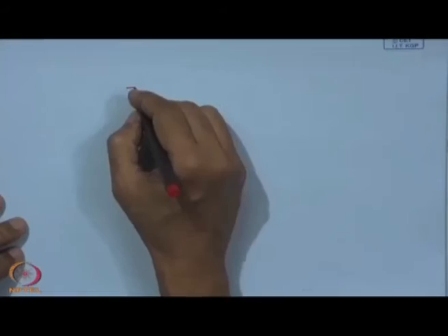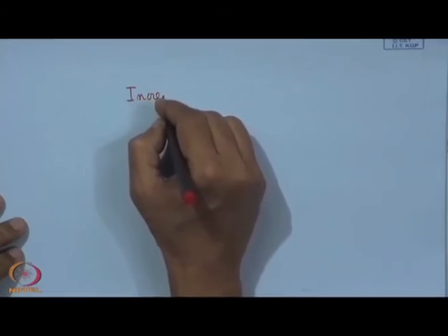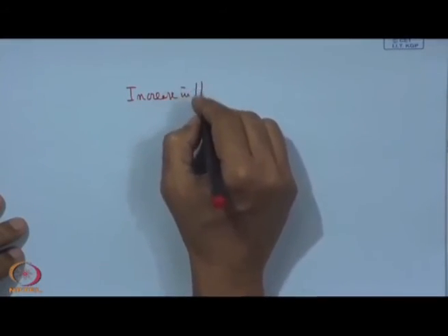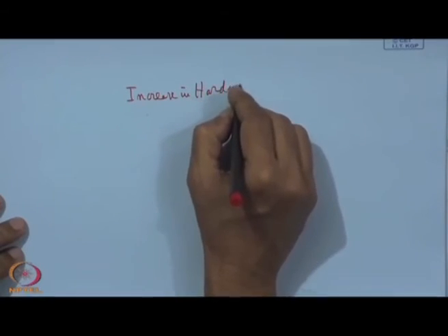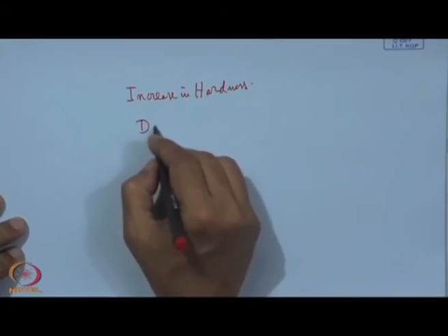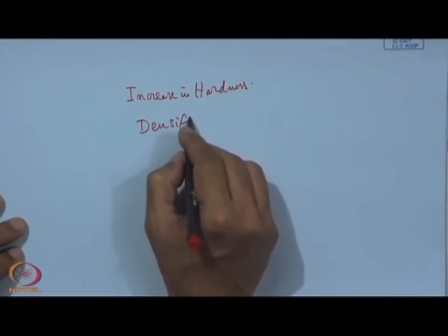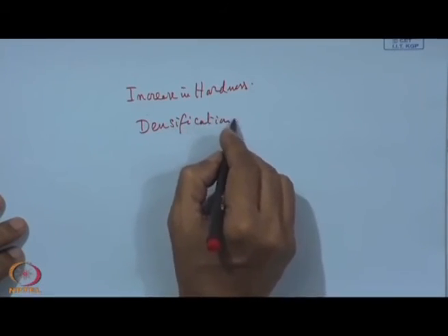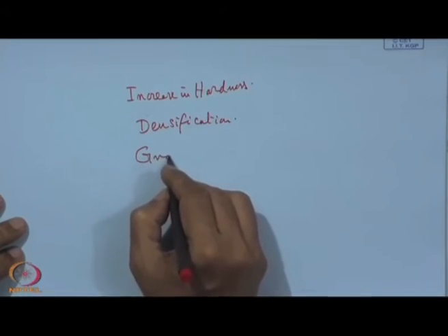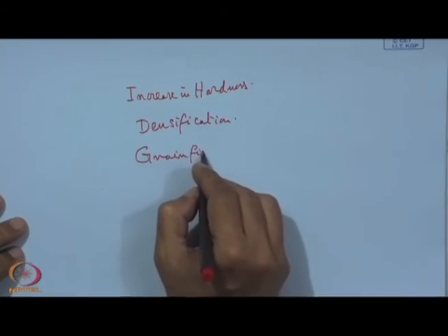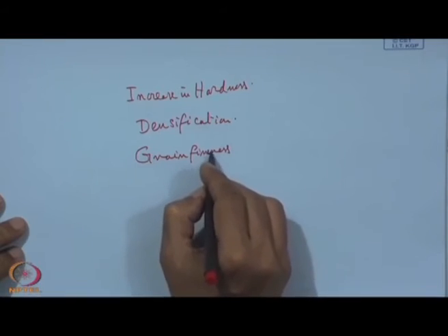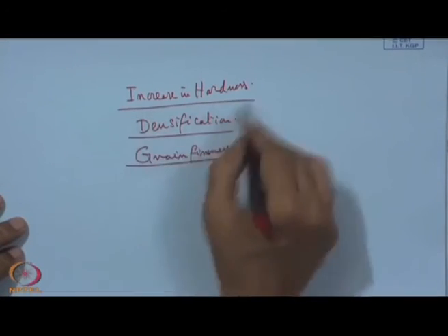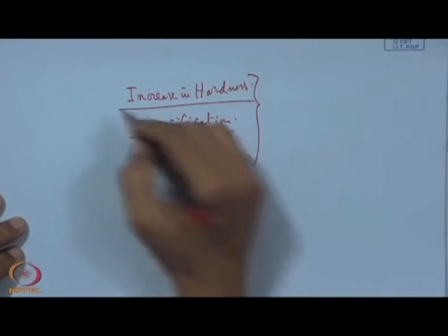Now, to get rid of that, if we have this pulsing, in that case what we have seen is an increase in hardness, densification, grain fineness, so these are the immediate things one can look into.